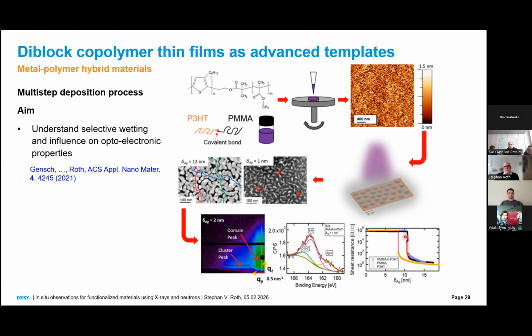Okay, IsGISAXS is, I would say, the classic program. It is really, as it says, Island GISAXS. You have a cluster layer, one spacer layer, and a substrate. This is the reference program developed by Rémi Lazzari, and we also use it today. Here for all metal on polymer, hybrid materials, I think it's fully sufficient.